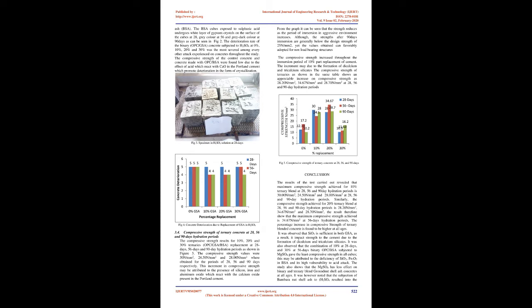3.3 Effect of sulfuric acid on binary and ternary concrete at 28, 56, and 90 days of hydration. The effect of 20% sulfuric acid on compressive strength of groundnut shell ash, GSA, for 0%, 10%, 20%, and 30% cubes for 28, 56, and 90-day hydration periods were compared, as shown in Figure 3, and performance index shown in Figure 4. The concrete deterioration rate ranges from severe to very severe attack, 4 to 5, at 0%, 10%, 20%, and 30% percentage replacements all through the age.